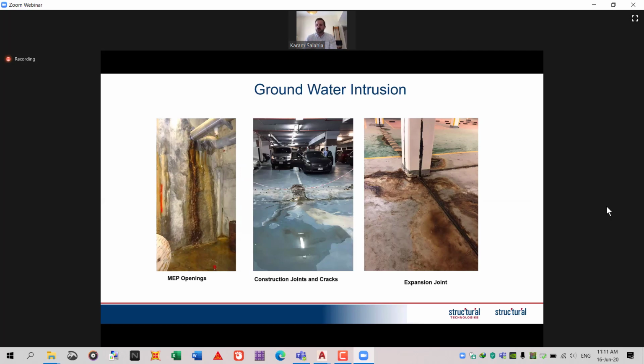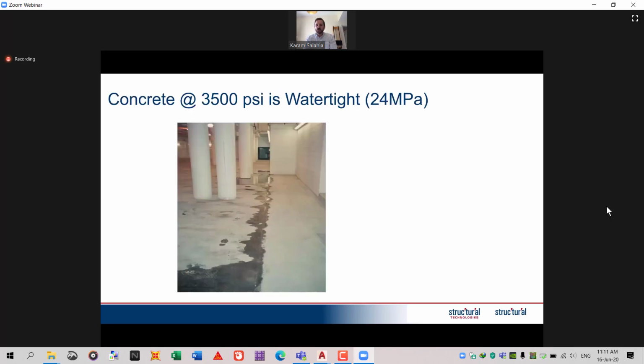So I thought I'd just start off with some photographs so that everyone is familiar with what we're talking about. So, unfortunately, most of the basements here do actually leak. So water can come in through MEP openings. It can come in through cracks or construction joints, or it can come through expansion joints. Interesting fact is that concrete above 24 MPa is actually watertight. But that's except at the joints, the cracks, and the honeycombs. So it's generally at the defects. Wherever you have a defect or a concrete interface, a construction joint, that's where the water can come through.